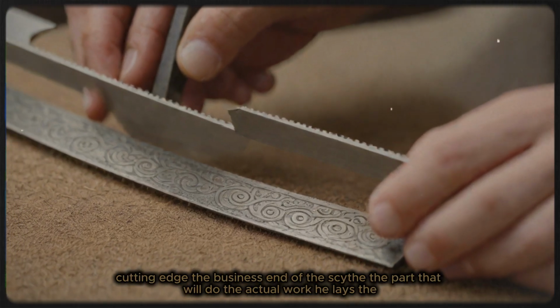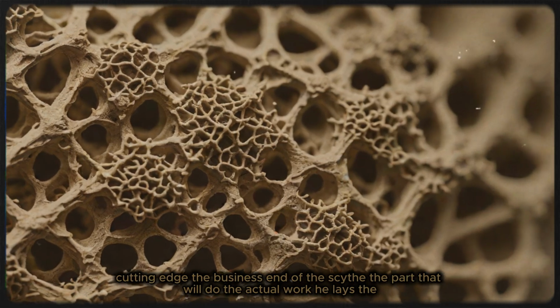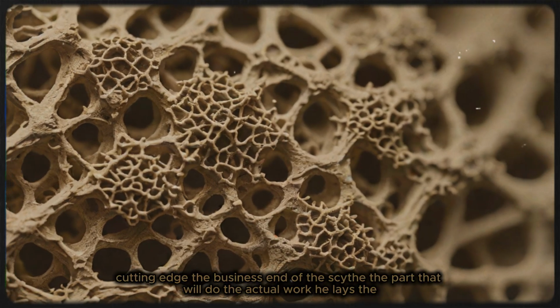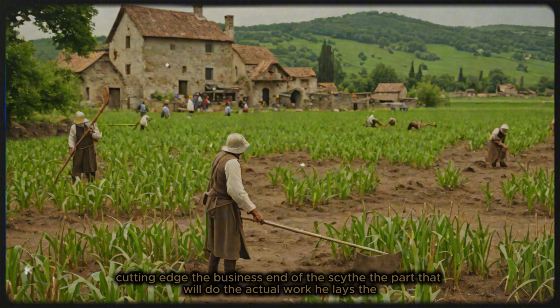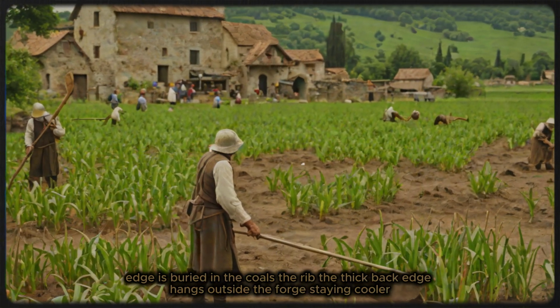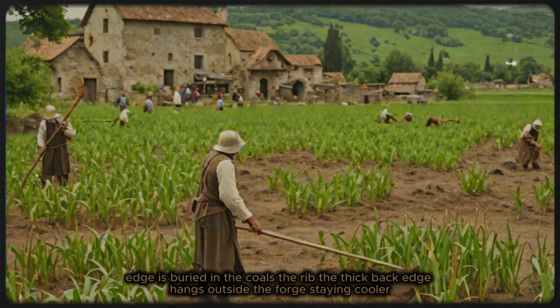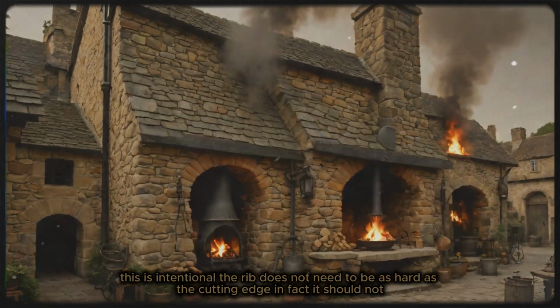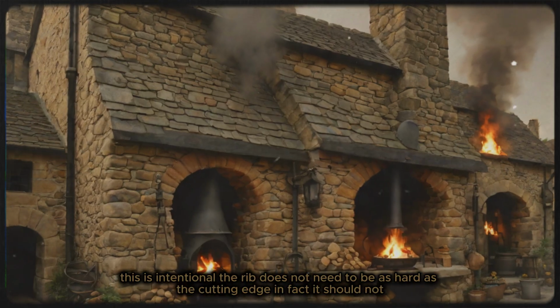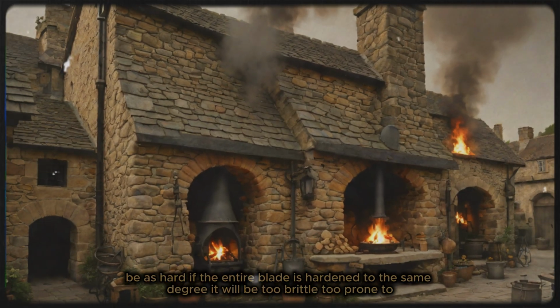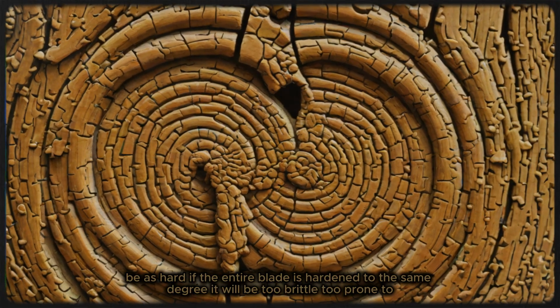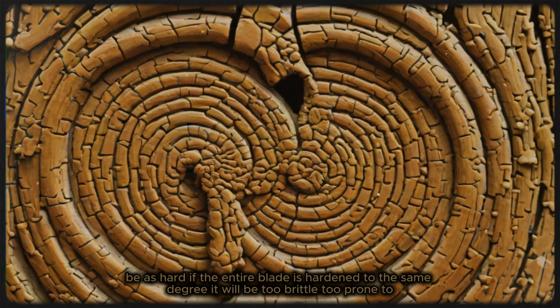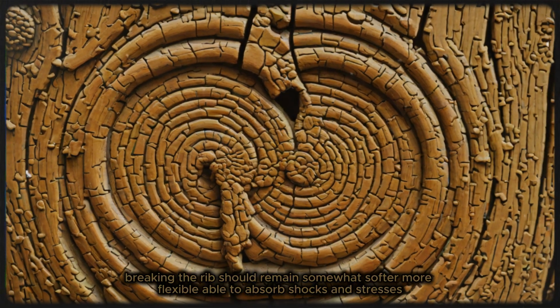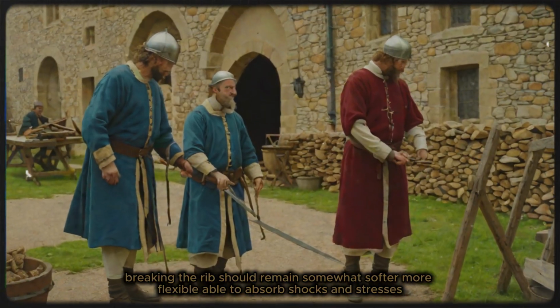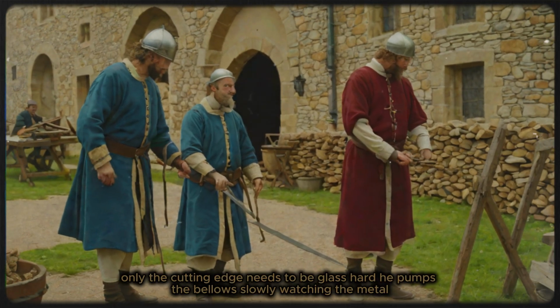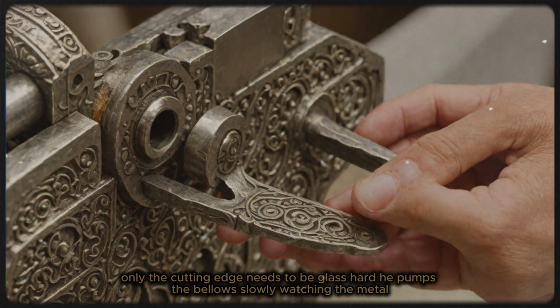He starts with the cutting edge, the business end of the scythe, the part that will do the actual work. He lays the blade across the forge so that the first foot of the cutting edge is buried in the coals. The rib, the thick back edge, hangs outside the forge, staying cooler. This is intentional. The rib does not need to be as hard as the cutting edge. In fact, it should not be as hard. If the entire blade is hardened to the same degree, it will be too brittle, too prone to breaking. The rib should remain somewhat softer, more flexible, able to absorb shocks and stresses. Only the cutting edge needs to be glass hard.